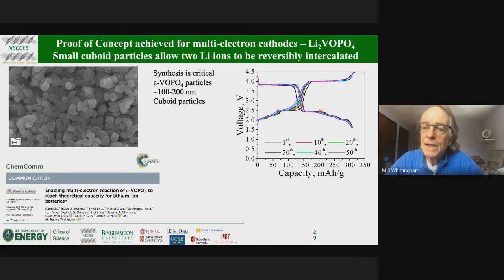And you can see there's a number of bumps in here. This is where the lithium ions are ordering. And in fact, at room temperature, if you let it stay, you'll get different crystal structures in here. But when you're moving lithium ions in and out, it behaves as a single phase material.